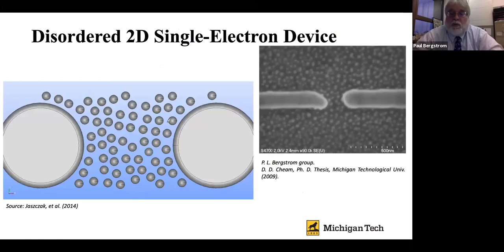But because these were multiple dot devices, again, we have multiple quantum dots, and because we had gaps that were modest, these gaps were probably on the order of anywhere from 17 nanometers for the smallest devices, upwards of maybe about 100 nanometers for the larger devices, we know now we have more than one quantum dot that actually might be participating in the conduction of the device. So we needed to understand this better. We needed to study this. And so the experimental device is complex. The experimental output characteristics are complex. So we needed to understand the physics of this better.